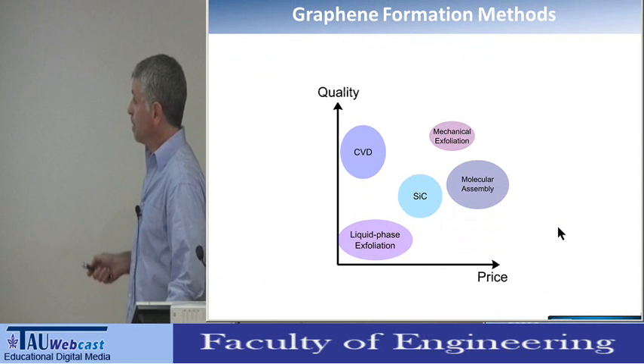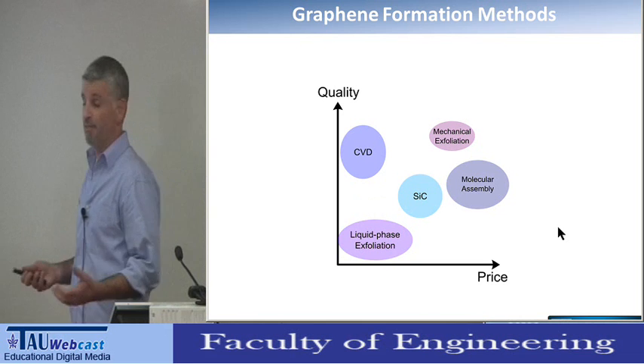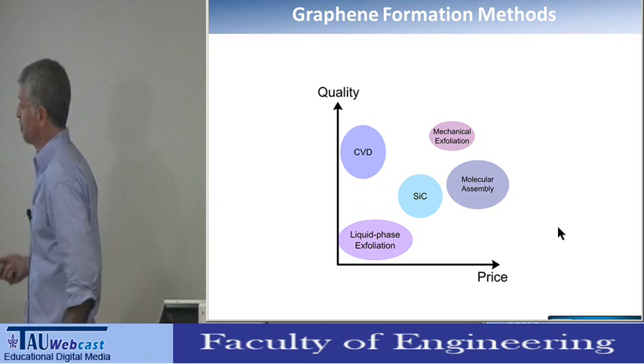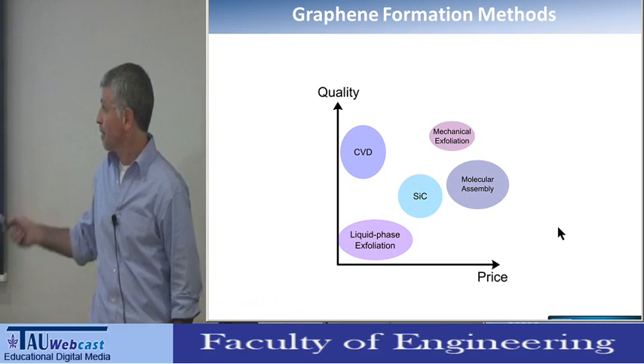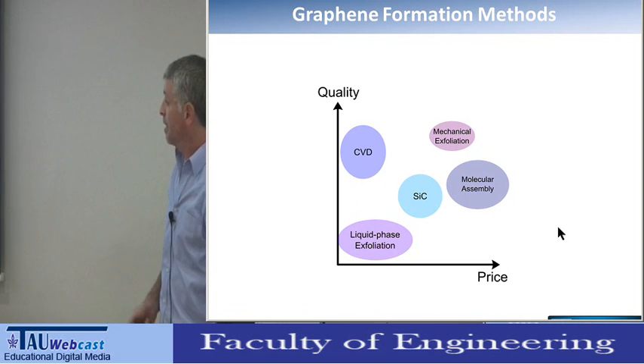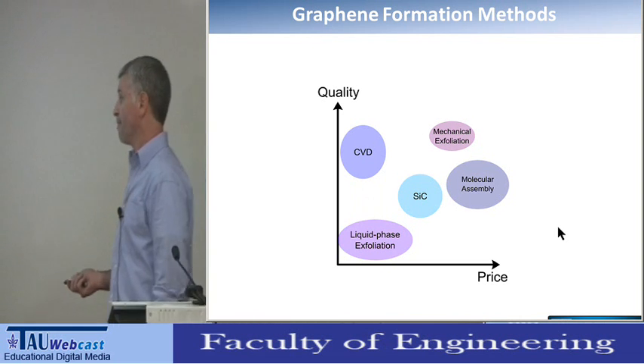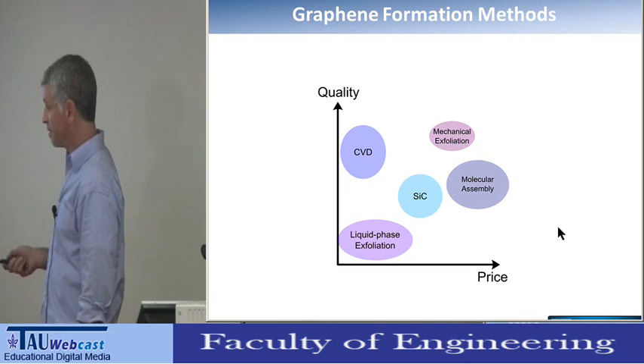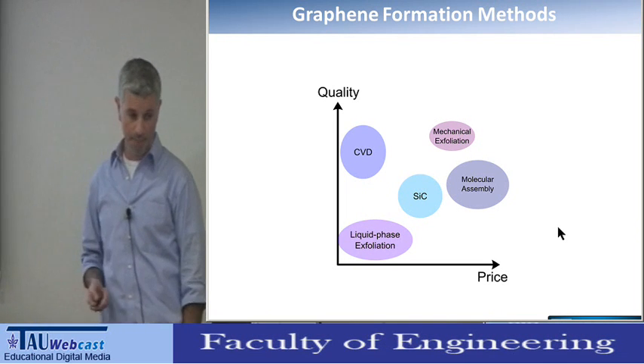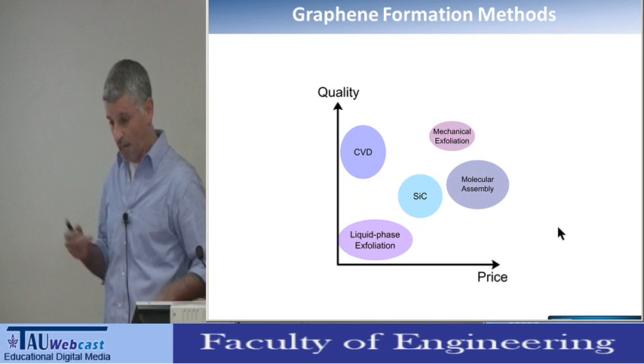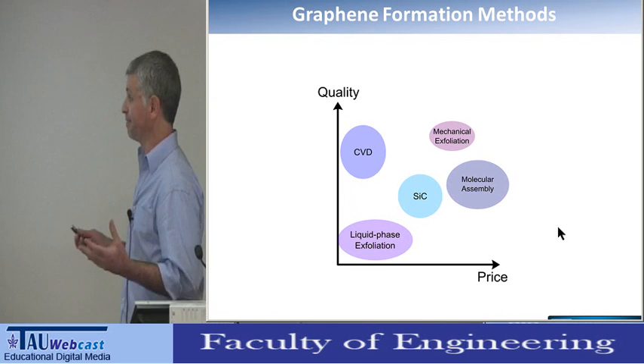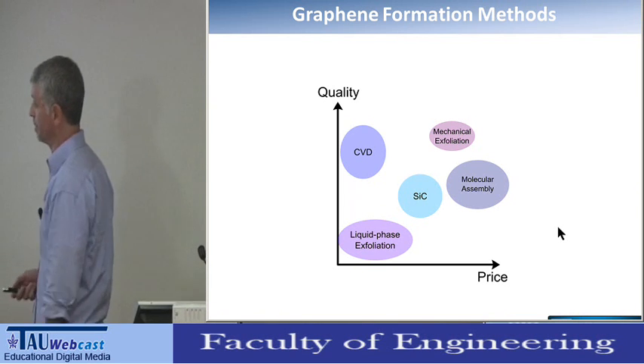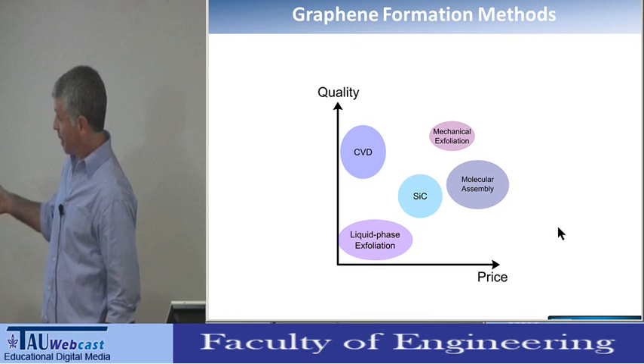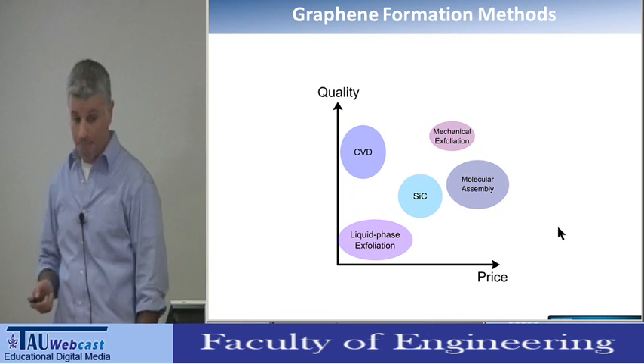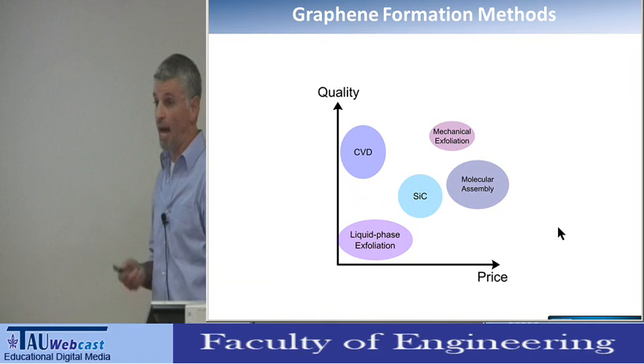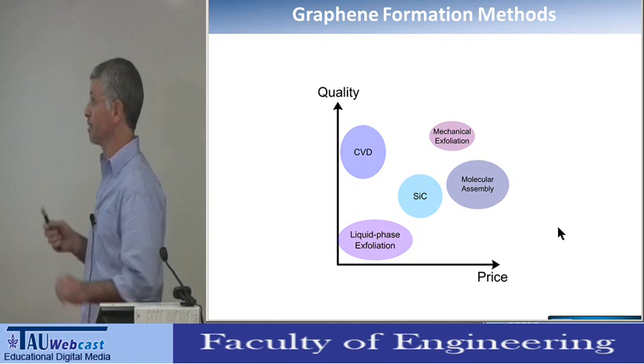And when you look at the different methodologies available to make graphene samples, you have here the quality of the graphene and the price. You can see first that liquid phase exfoliation is the easiest, cheapest way to do it. But then, of course, you get a very large quantity of material, but with poor quality. And then mechanical exfoliation is still the best way to get the highest quality graphene over very small areas.